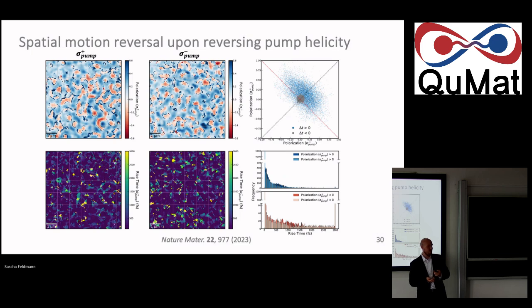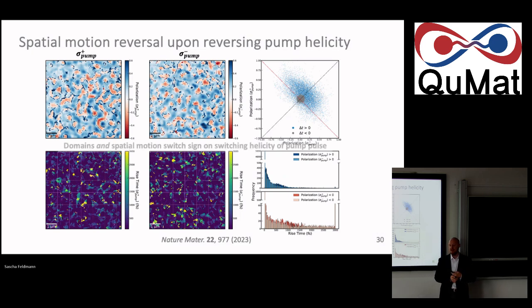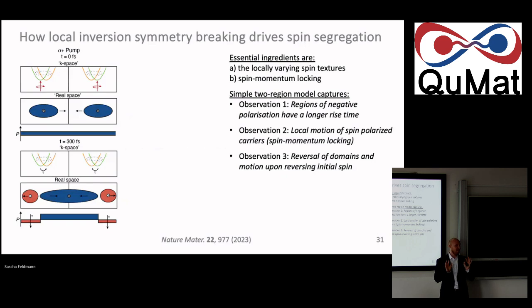Now, how can we piece this together and explain it? Domains and spatial motion and kinetics switch. How can we explain this? It's actually a rather simple model, but it should be enough to explain this. So I want, first of all, for my recipe, spin momentum locking as the rule of the game. Spin up goes this way, spin down this way. Okay. And it has to come from somewhere.